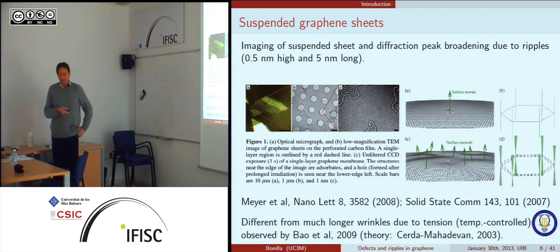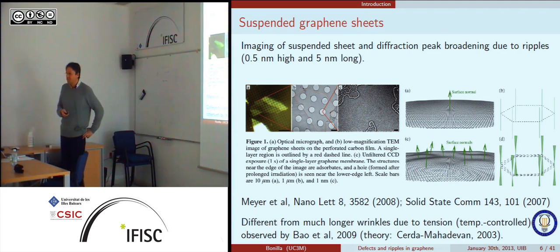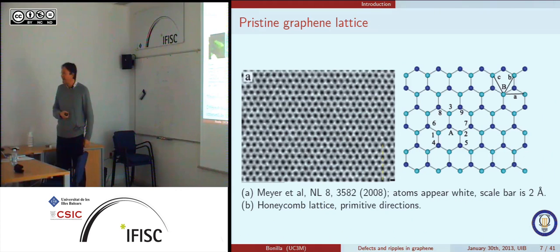Actually, the ripples I'm going to talk about are randomly oriented. They have a very small height, below a nanometer, and wavelength varies from 10 to 25 nanometers. There are other ripples you can create by taking a big graphene sheet, microns long, and pulling it, like when you have a plastic and you pull it, you see that wrinkles get formed. Those are also seen, but they are explained just by mechanical properties, like the sheet of plastic. So the ones I'm going to talk about are much smaller, and their origin is not as clear as the big ones.